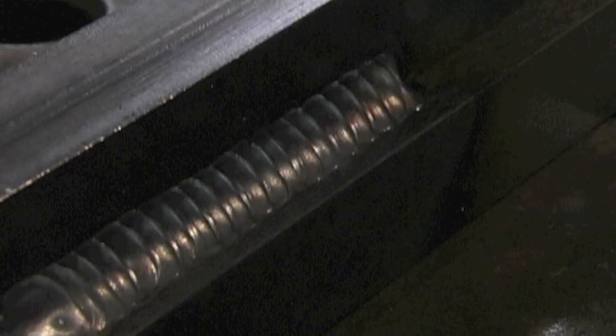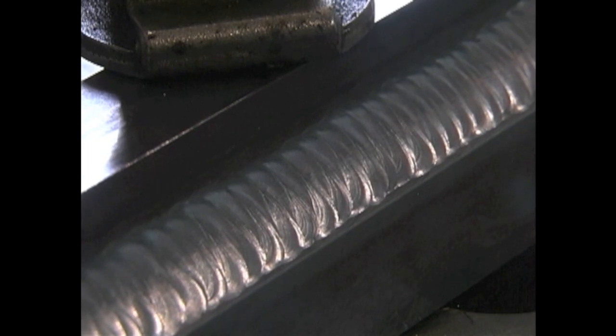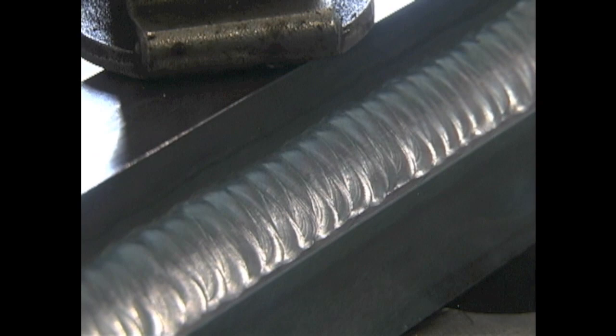That's a little cold. I was using about 150 amps with a one-eighth rod. I bumped it up a little bit to somewhere probably around 170 to 180 and dropped the rod size down to 3/32 and it feeds in there a little smoother. You don't have such a distinct cold chill line on the ripple and that looks a little nicer. This is a thick piece of 4130, so sometimes you got to add more weld than you can get in one pass. I'm coming across here with a second pass now. You could do this stacking them in there but I just chose to take a 1/8 rod and weave over it here and also feed just a little bit of rod in as I go. Again we're up around probably 170 or 180 amps here, this is using the Everlast 210 EXT, no pulse, just using it for its amperage. That 4140 welds like honey.